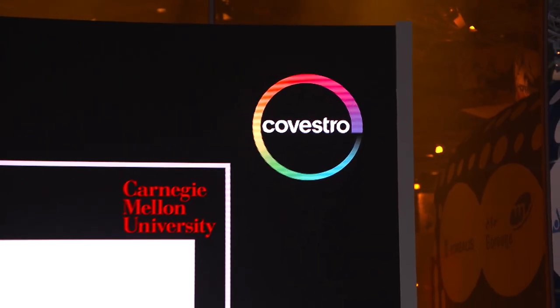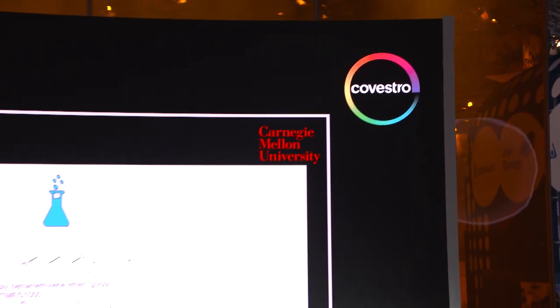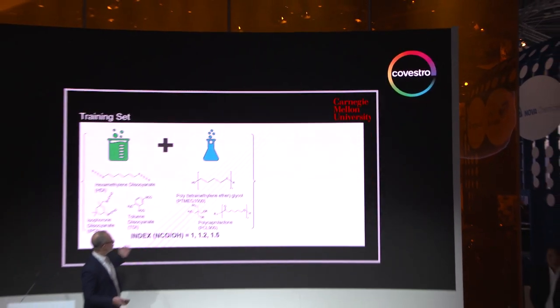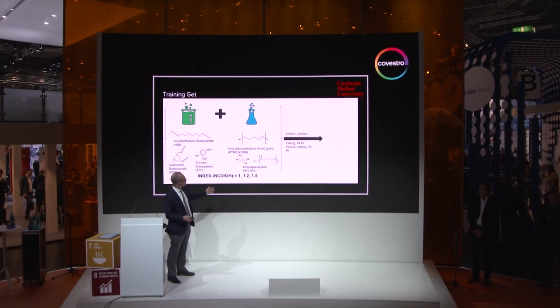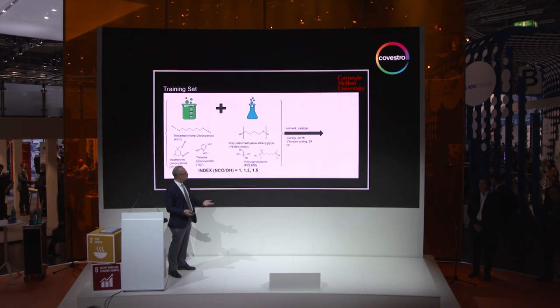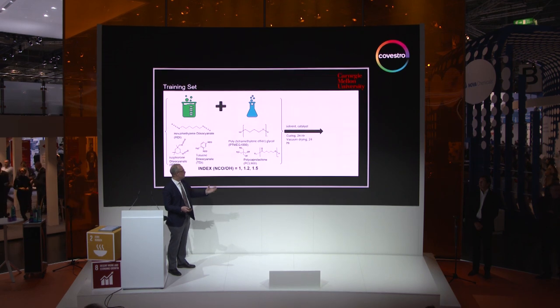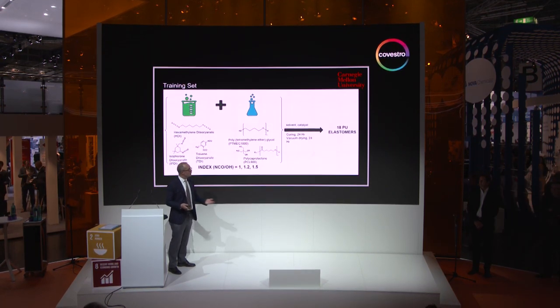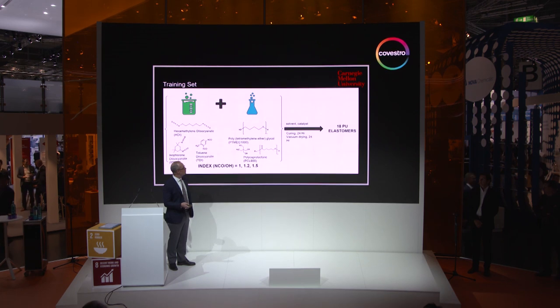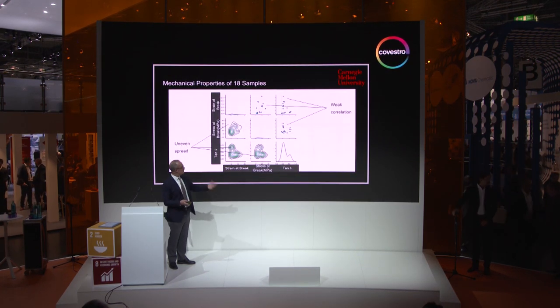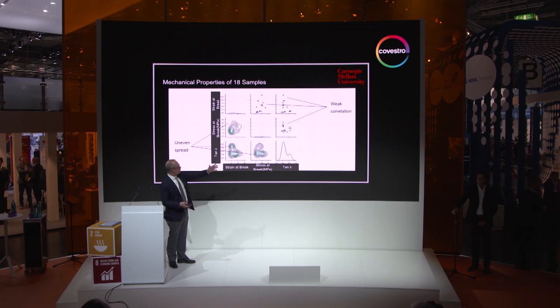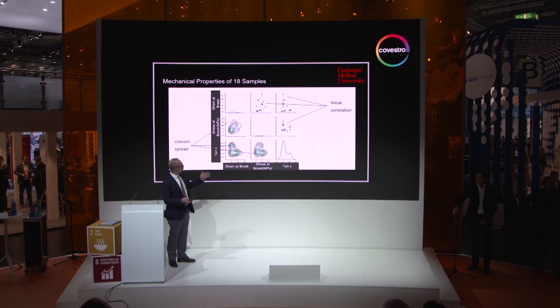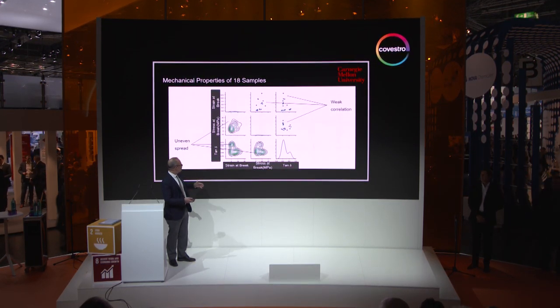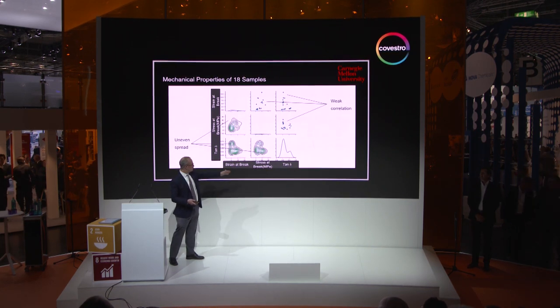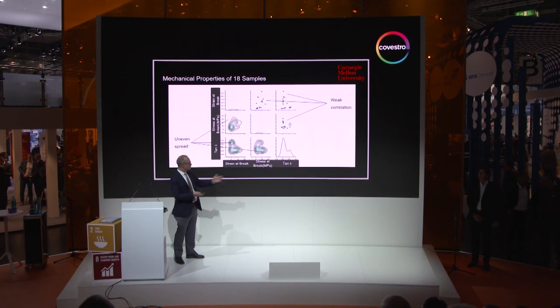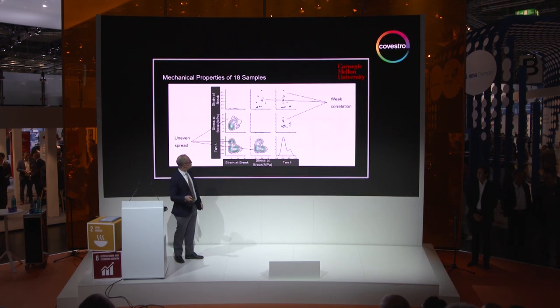So to make the samples, which were done in my lab at Carnegie Mellon, we're blending isocyanates and polyols. We're varying the ratios of these two, and then we're controlling solvent and catalyst, under constant curing conditions. Ultimately, we have a relatively small library of 18 polyurethane elastomers that we're going to use to train the algorithm. We start with a broad survey of the data, and basically what we're seeing here is that knowledge of the strain at break will not allow you to predict something like the stress at break or the ratio of the elastic and the viscous responses of the materials.